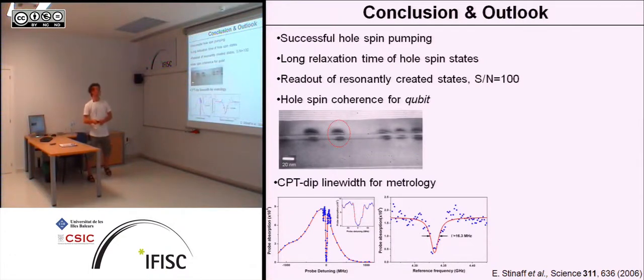Okay, so I conclude, and my outlook is, we succeeded in hole spin pumping. That was the first step in the roadmap of quantum information processing. We extracted a long relaxation time for the hole spin states, which is very important, especially also for quantum error corrections. We also succeeded in readout of resonantly created quantum dot states with a signal-to-noise ratio of roughly 100. But most importantly, we could show that hole spins are a very coherent system, much the opposite of electron spins, and that really opens a completely new field, because so far pretty much no experiments, at least in single hole spins, have been done in semiconductor materials.